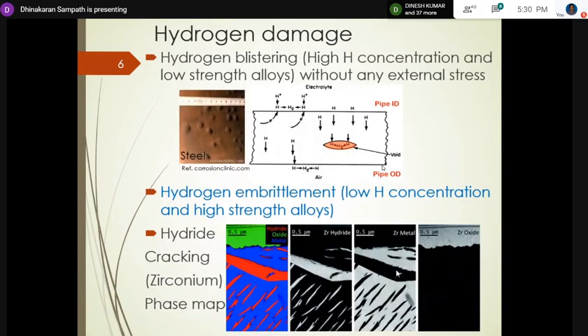So what hydrogen damage do we see? More broadly, there are about three types. First, hydrogen blistering, which occurs in low strength alloys, that means having low yield strength. In the presence of high hydrogen concentration, these are present in an electrolyte. Basically, the hydrogen is generated through an electrochemical process, and it splits into single H, which is called nascent hydrogen or atomic hydrogen, also called absorbed hydrogen. That is what enters into the metal.